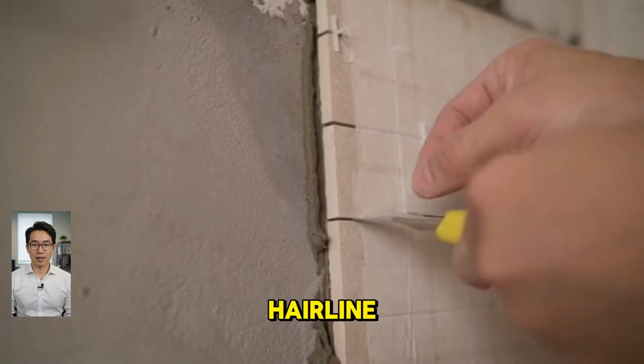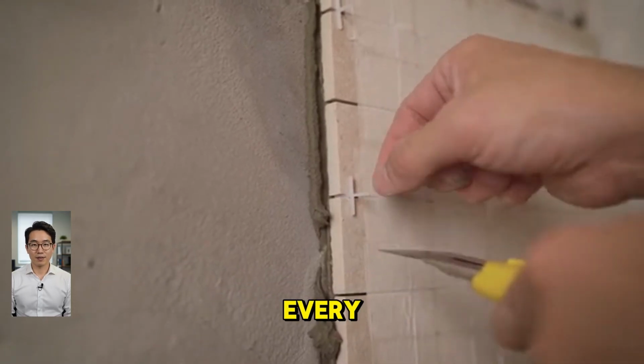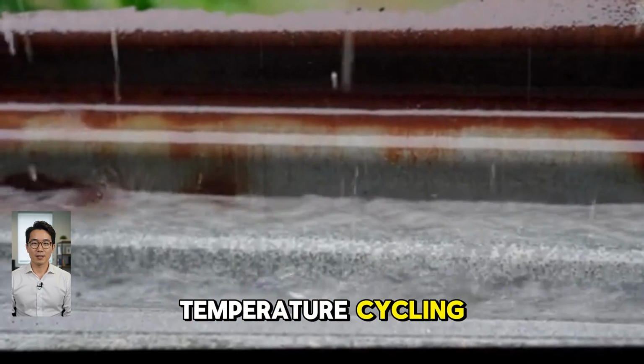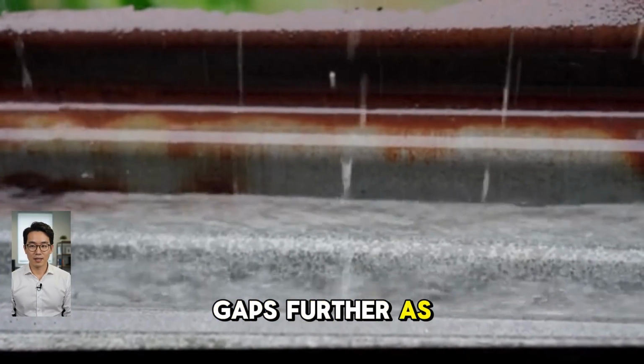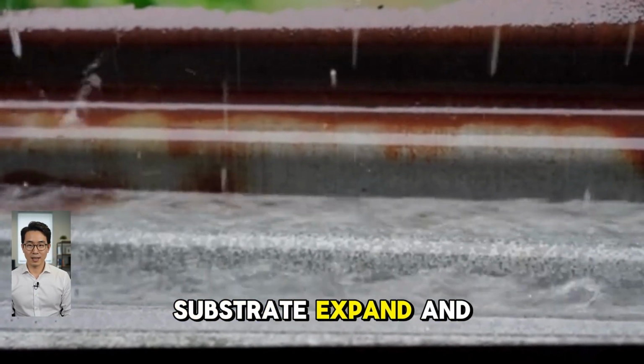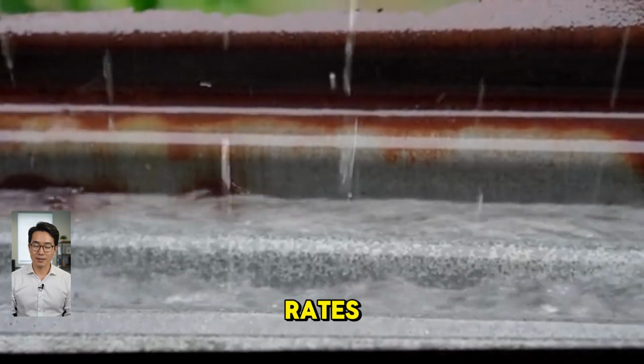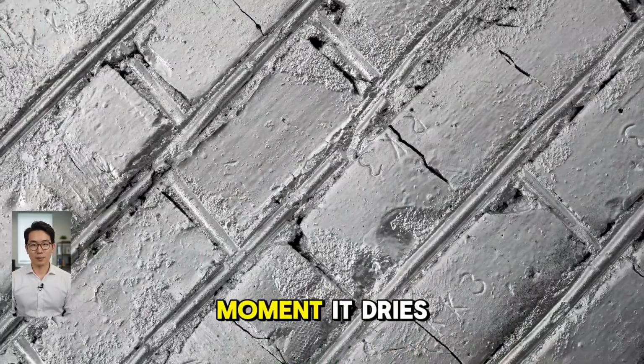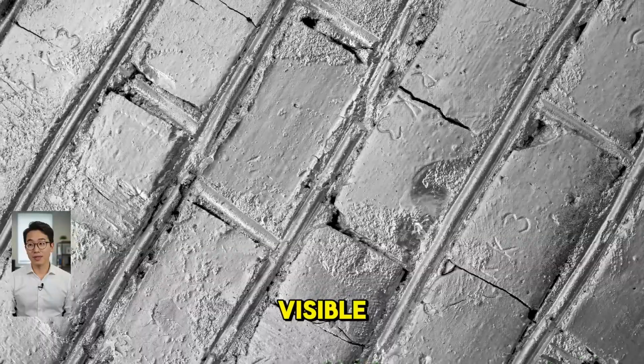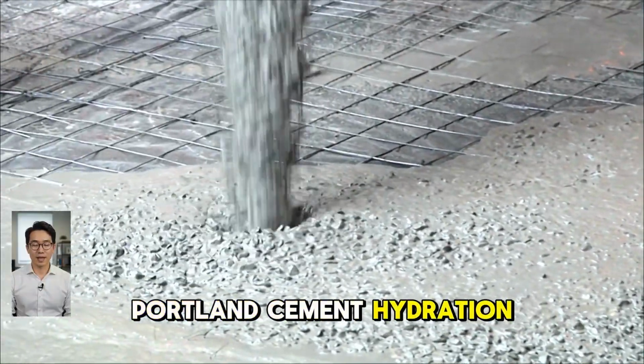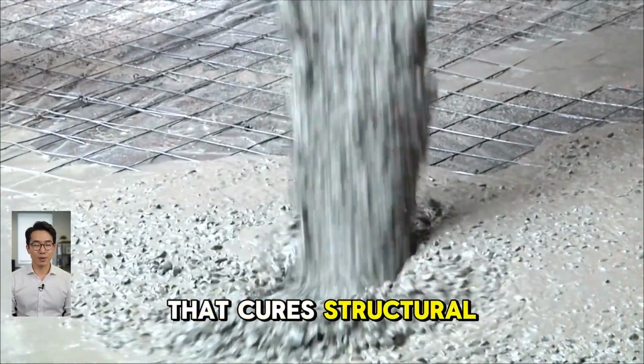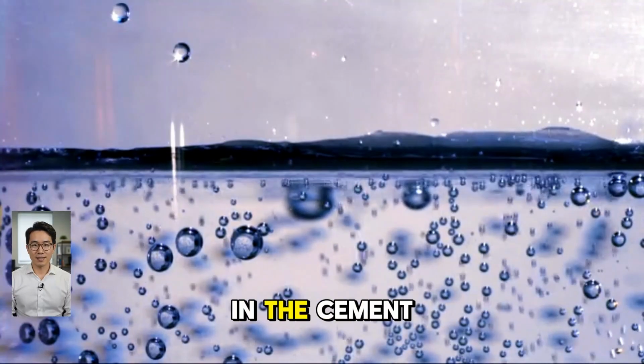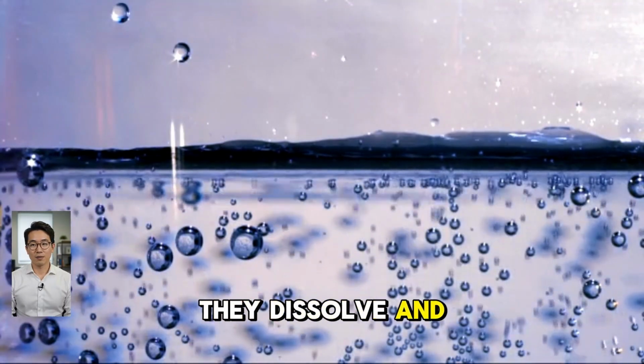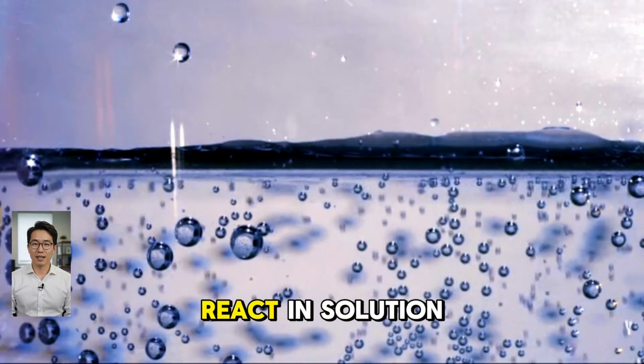This produces the hairline cracks that follow the perimeter of every conventional wall repair. Temperature cycling widens these interface gaps further as the repair material and the substrate expand and contract at different rates. The repair is a completed failure from the moment it dries, just not yet visible. Hydraulic cement sets through Portland cement hydration, the same chemistry that cures structural concrete. When calcium silicates in the cement powder contact water, they dissolve and the calcium and silicate ions react in solution.